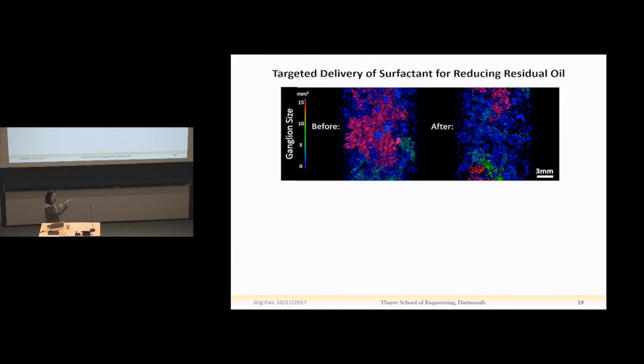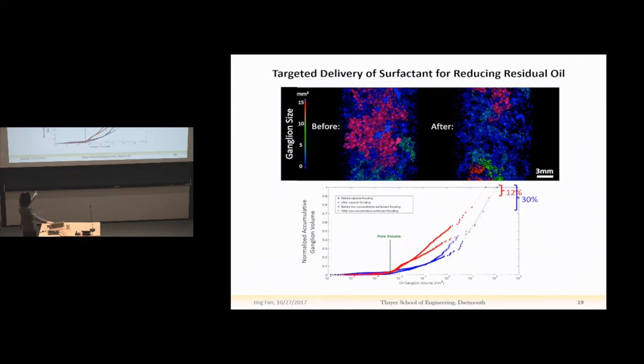And then we also compare this process with direct surfactant flooding, which means we dissolve the same amount of surfactant directly in water and inject this surfactant solution into the model porous media system. And we compare these two experiments, and we plot the normalized accumulative ganglia volume as a function of the oil ganglia volume. And the main takeaway point is that with the smart surfactant-loaded capsules, we observed a 30% reduction of the residual oil. But with the direct surfactant flooding, by injecting the same amount of surfactant, we only observe a 12% reduction of the residual oil.